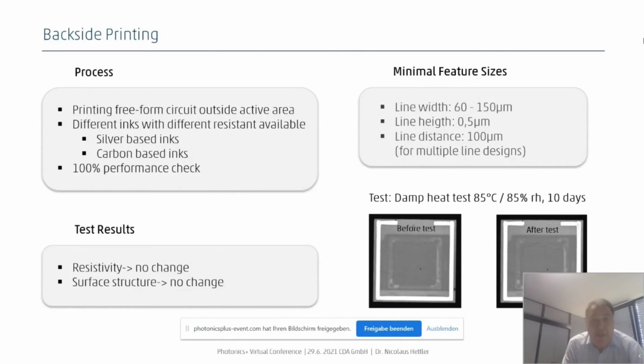So we have found another way how to bring the same functionality to the parts without using ITO. And this is very simple. I told you before, CDA can print. And what you see here, this white line on this DOE is a printed circuit. These circuits can be printed from silver-based inks or carbon-based inks. And of course, when we do this on large scale, there's a 100% performance check of the circuit performance after the printing.